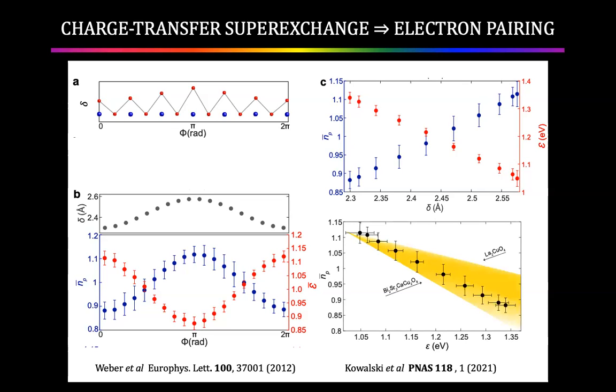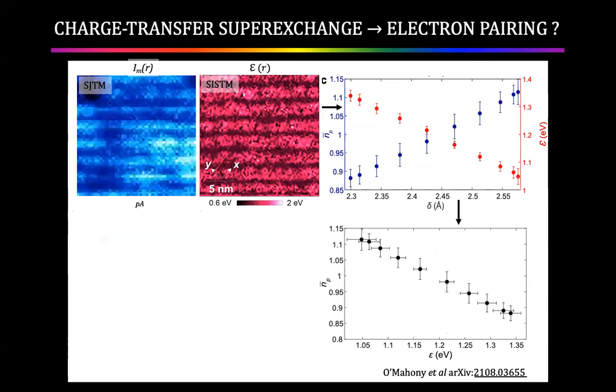Here is the cone of interest that came from the Kotliar and Haule prediction on this side, and from the Tremblay prediction on that side. Most cuprates, we believe, are inside this one. Okay, so here are the facts. There's a modulation in this compound. The Josephson critical current squared modulates at that period. The gap between the top of the lower band and the bottom of the upper band modulates.